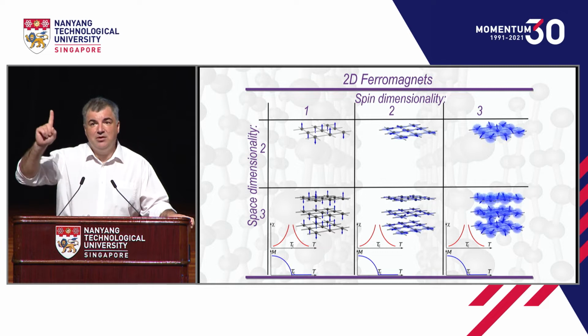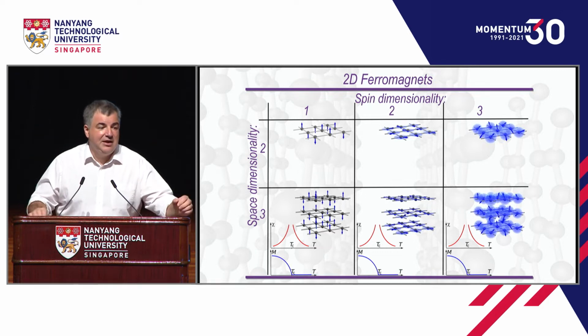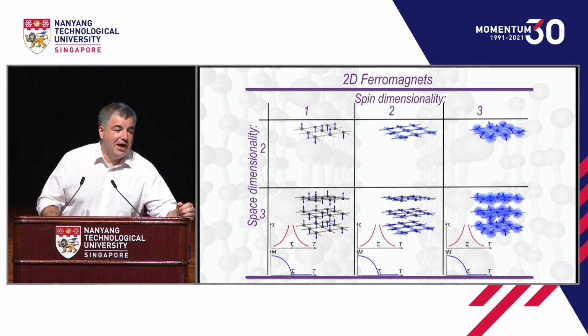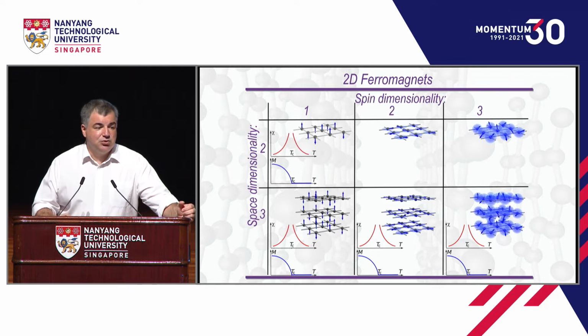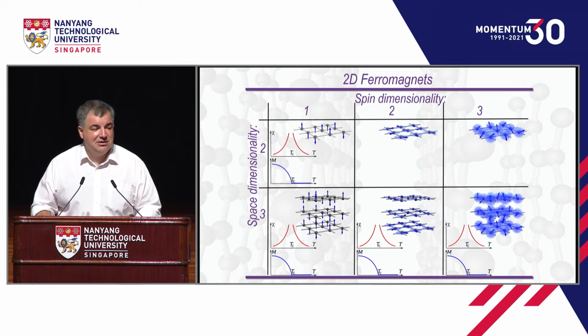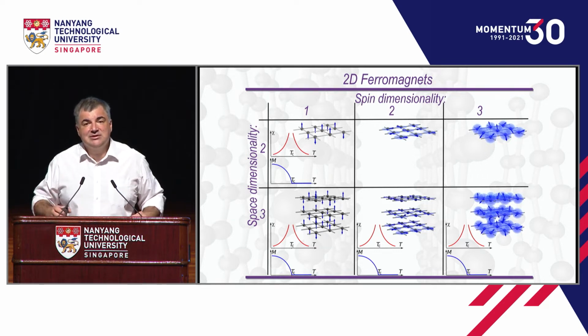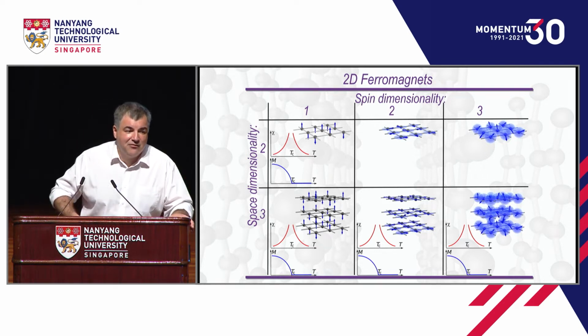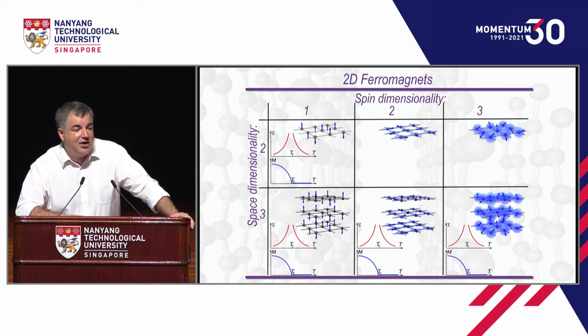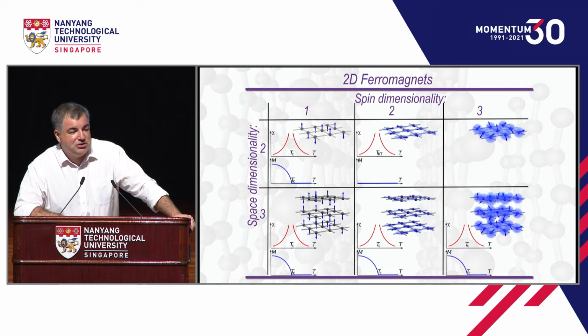So spins can only point up or down. That's the so-called Ising model. And in that case, in two dimensions, same as in three dimensions, there is a phase transition. So you heat up your system, it stops being ferromagnetic. Now, for the other two cases, say for the spin dimensionality 2, there is only the so-called Kosterlitz-Thouless transition, which is not a phase transition.